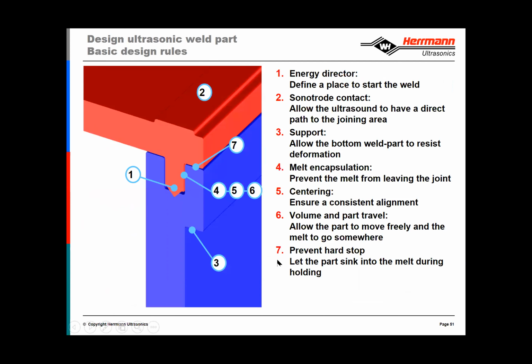And then finally, preventing a hard stop. We'll often see either a cosmetic gap or a bit of a gap in between the finished parts. We don't want to rely on the welding to stop when the red part contacts the blue part. We want the welder to do the work. So the welder has controls such as an encoder, and we can monitor the energy and power that's put into the part. And those controls are more reliable in stopping the welding process than relying on the parts to quote unquote bottom out.